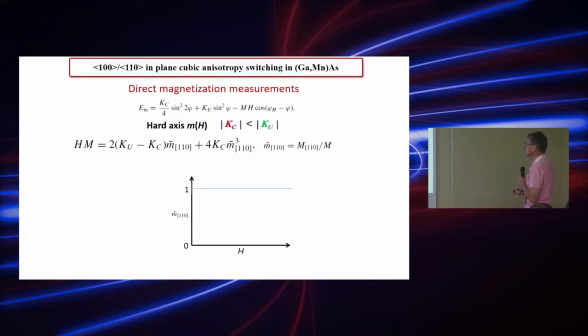So in order to answer this, we have to come back a little bit to very simple mathematics, and we have to solve this equation, which is not particularly difficult. We can introduce relative units of the projection of the magnetization along the 110 orientation. This is exactly what we measure in SQUID magnetometry. We apply a magnetic field along this orientation, and we look at the value of the magnetic moment, the projection of the magnetic moment on this orientation.